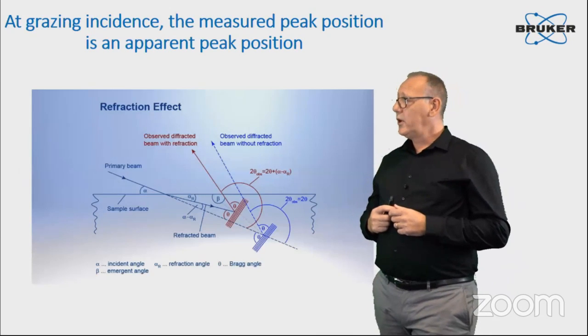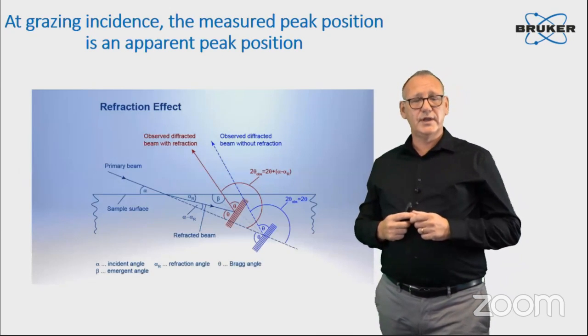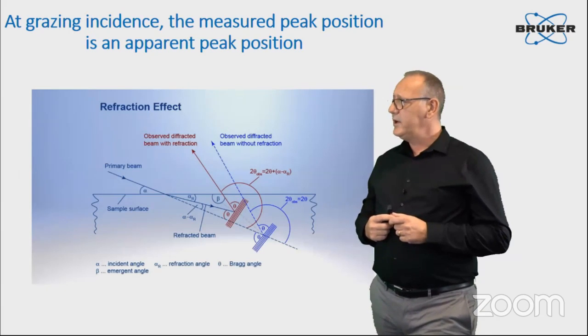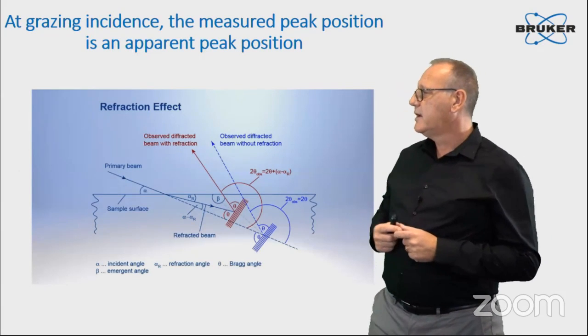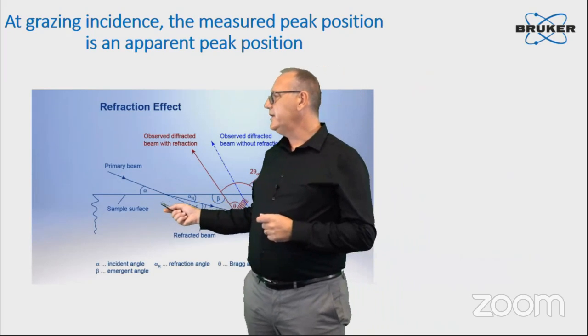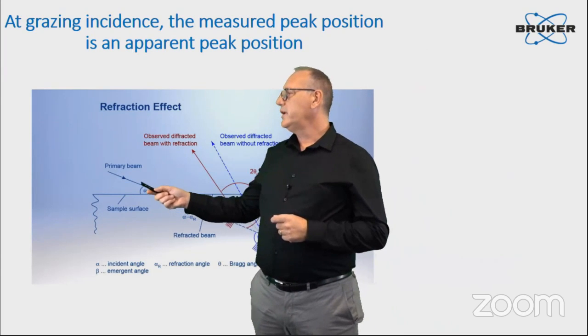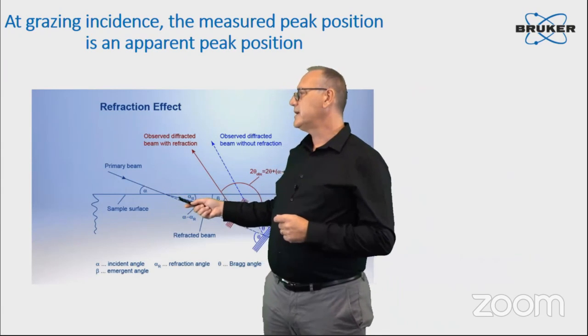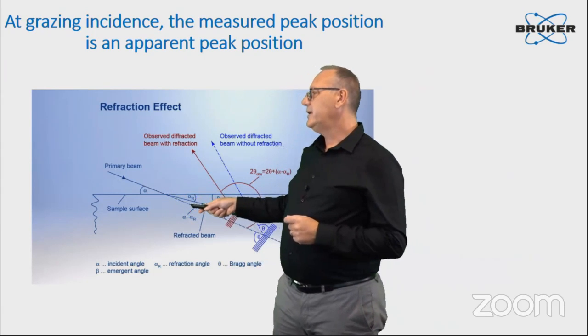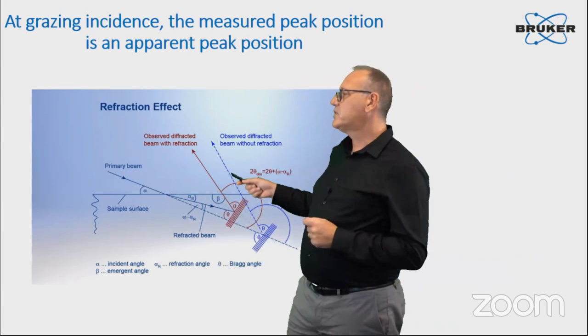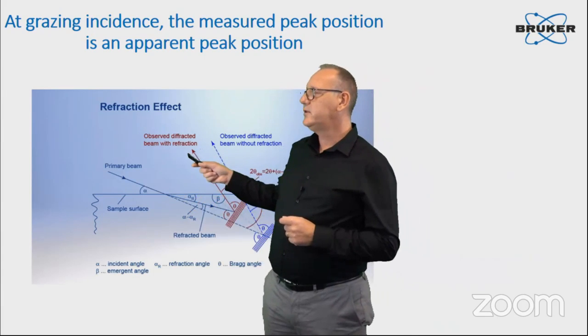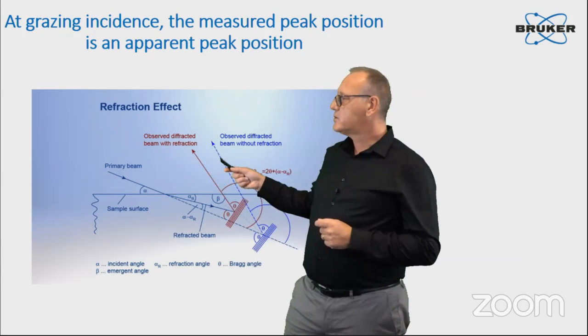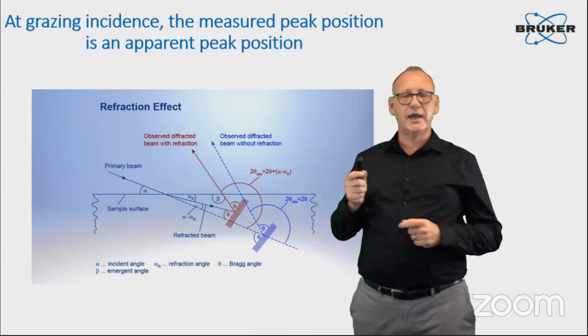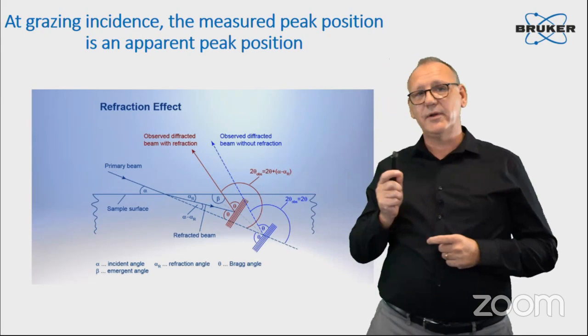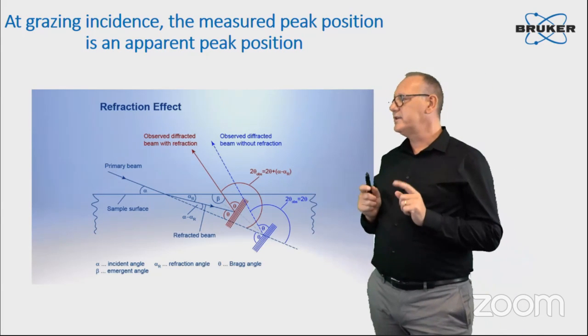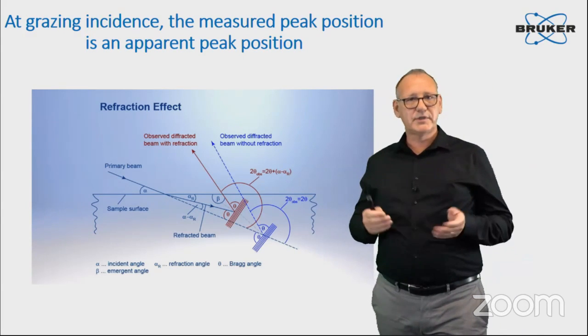What we've also heard is the so-called refraction effect. If you have a very low incident angle at your surface, you will have a refraction effect at the interface. That means that the incident angle you thought you had set up is actually modified at the interface. It also means that the diffraction peak position you would have expected is shifted towards a slightly higher angle. So the position you measure in GID is in most cases an apparent peak position, and you also have to take this into account in your peak position evaluation.